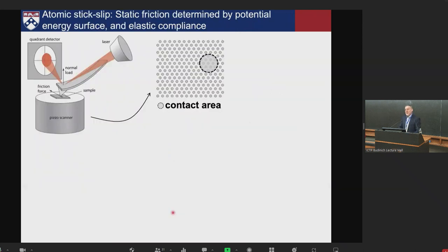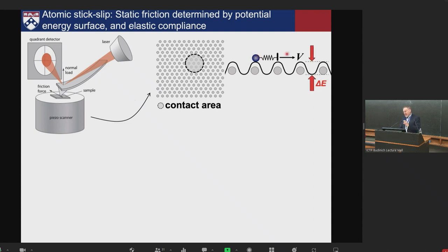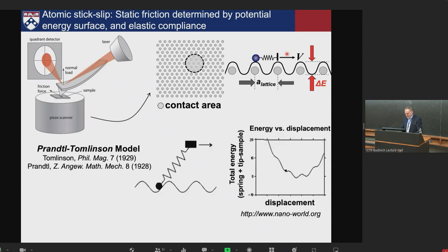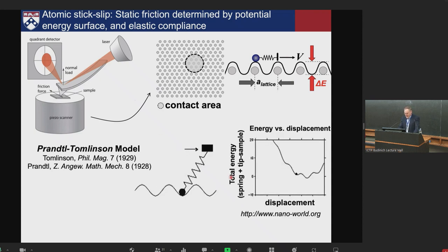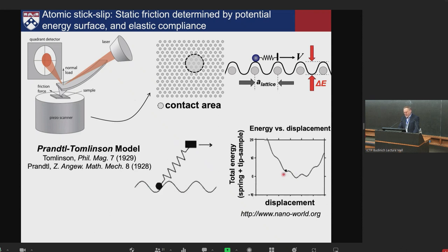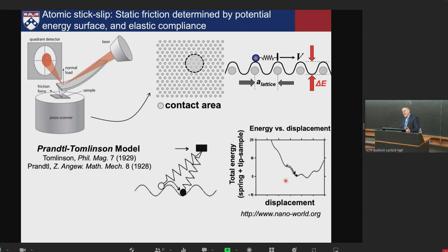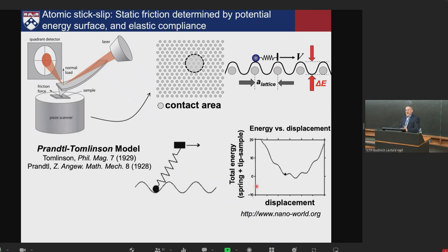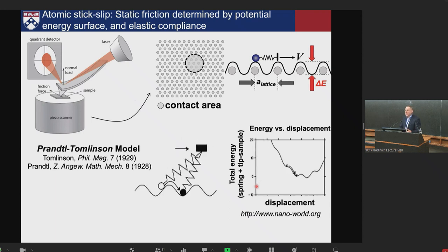Now, when we slide on these crystals, even though it's a single layer thick, if it's ordered, we often see stick-slip friction, which I think many here are very familiar with, ways to describe periodic stick-slip friction using things like the Prandtl-Tomlinson model, where you take a rigid potential, reduce all the degrees of freedom of the tip to a single point particle, an atom as it were, connect it to a spring, and there's some energy corrugation to that potential energy surface. There's some spacing of the lattice, and Prandtl and Tomlinson each worked out that you can get these instabilities as you slide. So as you pull, the little energy minimum you're in gets shallower and shallower until it disappears, at which point you'll slip to the next position. And that's at zero temperature. Of course, at finite temperature, thermal excitations will help you slip even earlier than that.